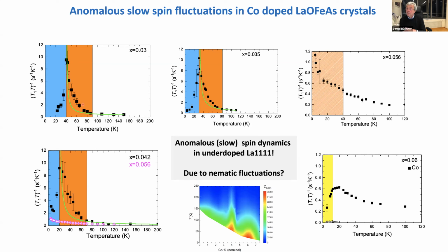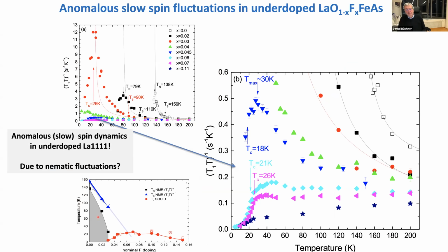Yes, there is a way. It's fluorine doping, out-of-plane doping, which should be really perfect if the crystals are nice. Luca? Just a comment: whether you dope with fluorine or cobalt, you get the disappearance of the magnetic phase at about the same doping. For fluorine doping, the phase boundary, at least as far as we know, is sharper, and it is at slightly smaller concentrations, about 3%. For cobalt doping it's 4%, but it's nearby. We are discussing real samples, with 3% fluorine doping and 4% cobalt doping. That's okay given the precision of measurements. It could be that fluorine doping is slightly more efficient, but the difference is pretty small.